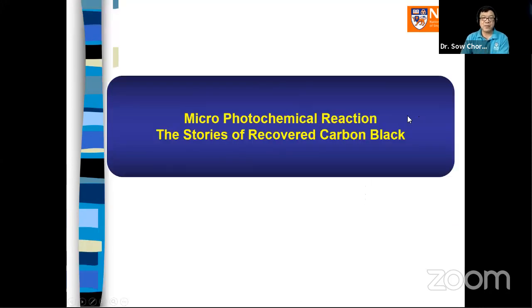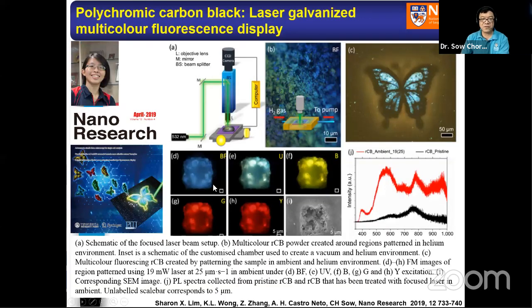And we also use this particular technique to do some modifications of chemical stoichiometry of recovered carbon black. Very cheap and economical material. And it looks black. But when you use a laser beam to focus on it, you see this work from Sharon, it generates very beautiful fluorescence color, because the recovered carbon black is just, you know, we buy it off the shelf, very cheap. Consider a lot of contamination.